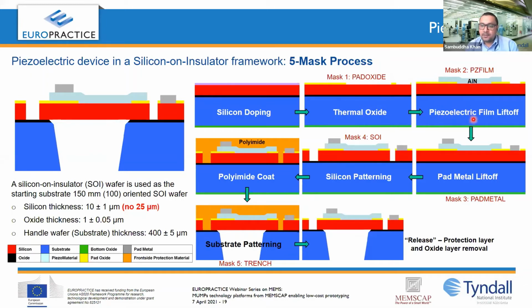Once the piezoelectric film is deposited, the wafer goes into pad metal deposition. That is also done via a lift-off process. Once the pad metal is deposited, you get a connection to your piezoelectric film, and then the silicon processing starts. So you have an SOI mask, and SOI is to pattern the top device layer on the silicon. Then it is required to pattern the trench mask from the backside, and therefore a polyimide layer is deposited to protect the top layer of the piezo film.